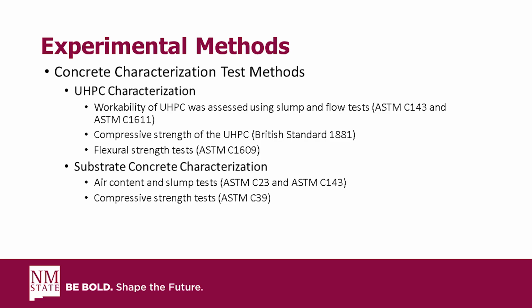For UHPC characterization, we wanted to look at workability, and this was assessed using the slump and flow test. Slump was run in accordance with ASTM C143, and flow with ASTM C1611. We also need to assess compressive strength to make sure we do have UHPC with that 17,000 PSI requirement. We use the British standard for this, which uses 4x4 cubes. And we also assessed the flexural strength on one of the mixes, which was run in accordance with ASTM C1609.